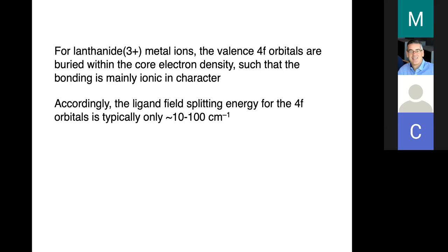Because these 4f orbitals don't have much overlap with ligand orbitals, the ligand field or crystal field splitting energies are, instead of many thousands of wave numbers, usually only many tens or a few hundred wave numbers, and perhaps, as we'll see, getting up to 1,000 wave numbers. But that is an order of magnitude or even two smaller than usually observed for transition metals.